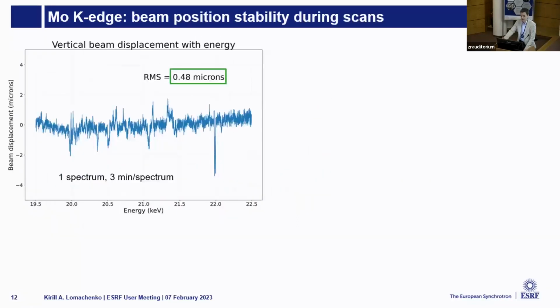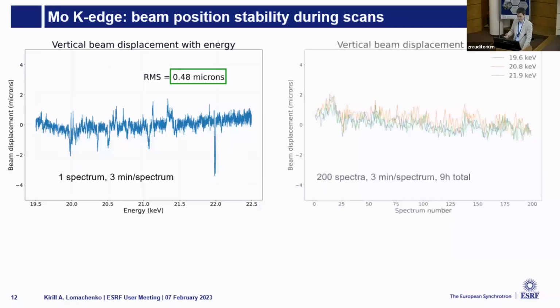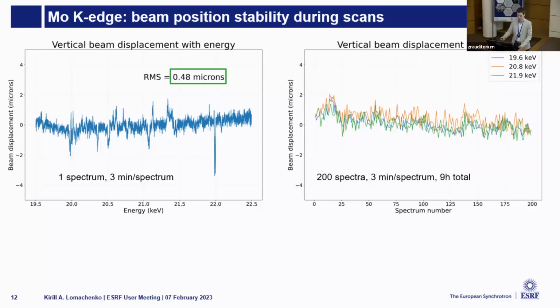Then you need to be sure that your beam doesn't move when you measure your spectra, because if the sample is small and the beam moves a lot, then it's not good. So here for one scan at the molybdenum edge, you can see the beam position for a large beam, a half by half millimeter beam, so 500 by 500 micron. The beam movement does not exceed 1 micron. And the spikes seen here are actually not movement of the beam, but instabilities in the optics. So it's not a movement of the beam, but the way we measure this position.